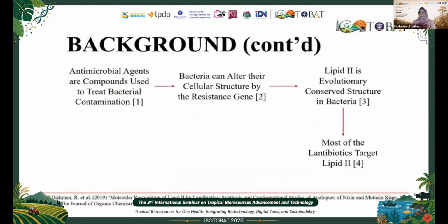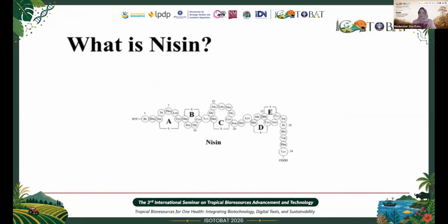A variant of antimicrobial agent that is quite well known for its ability to target lipid 2 is nisin, because it targets the most crucial part of lipid 2, namely pyrophosphate. This is the structure of nisin. Nisin's structure is characterized by the presence of non-standard residues such as dehydroalanine and dehydrobutyrine. It also contains rings called thioether rings. Rings A and B bind to pyrophosphate in lipid 2, while rings C, D, and E form pores. Indeed, this dual mechanism makes this variant quite well known among several antibiotics.